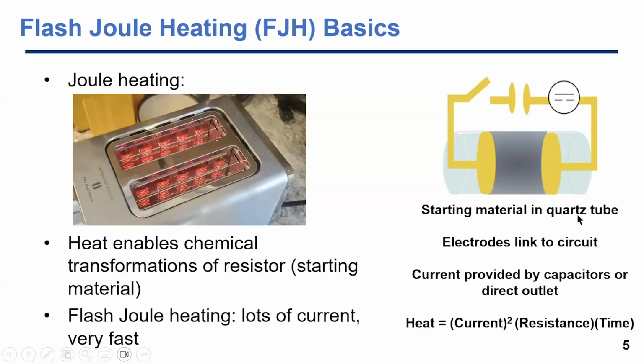But the idea is to take some material, put it between 2 leads. The material has to be somewhat conductive because we're going to drive a current through this. You don't want it too conductive because it's just a wire, the current goes through, you don't get much heat. So you want something that's somewhat resistive, somewhere around 1 ohm to 50 ohm resistance. And then you will get heating, particularly at hot spots.